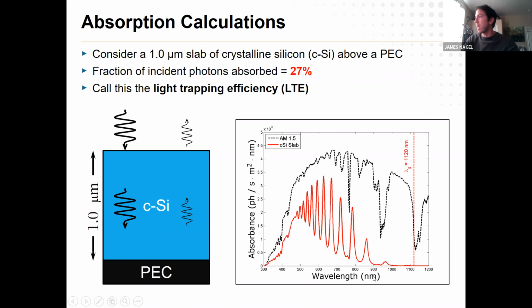And the red curve is the actual absorption of photons in this particular system. And you see this weird effect where it just kind of goes bonkers. So what you're seeing is at some frequencies, that back and forth reflection is actually destructively interfering with the initial bounce, so that I get just no reflections at all, and everything just gets trapped inside here. But then the price of that is you move off the frequency a bit, and the opposite will happen, where now they all constructively interfere and maximize reflections. And that's why I get a minimum in my absorption.